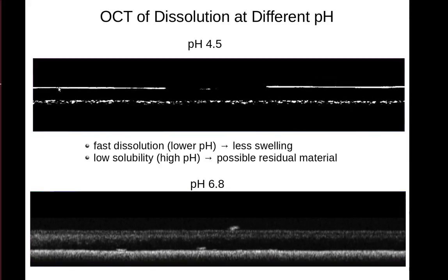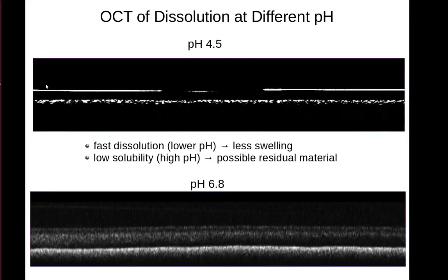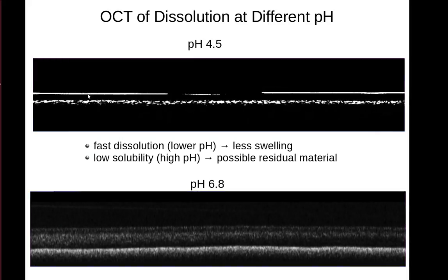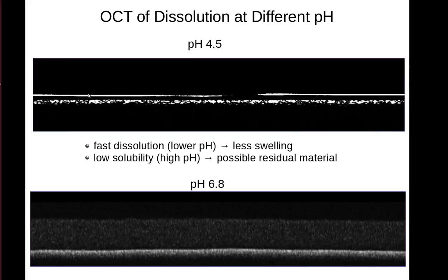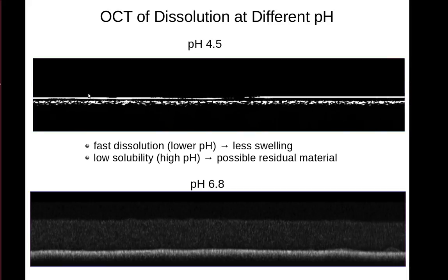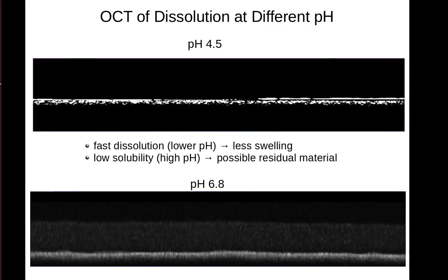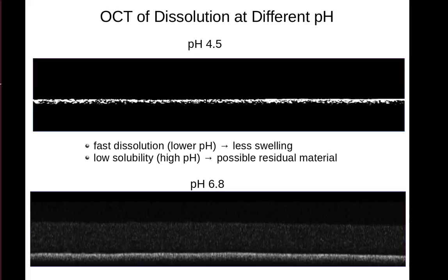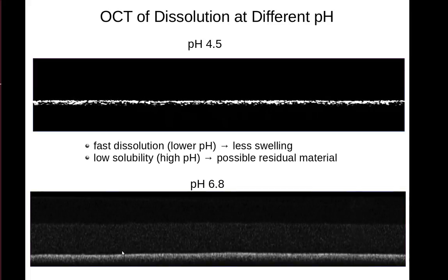Again, at 4.5 we see that the polymer dissolves almost from the surface downward, and relatively quickly. This experiment at 4.5 was probably on the order of about an hour. At a pH of 6.8, the film undergoes tremendous swelling before it finally dissolves. It looks like this experiment was cut a little soon. There's still some residual polymer that's apparent there. But it did swell before it was able to dissolve from the microscope slide surface.